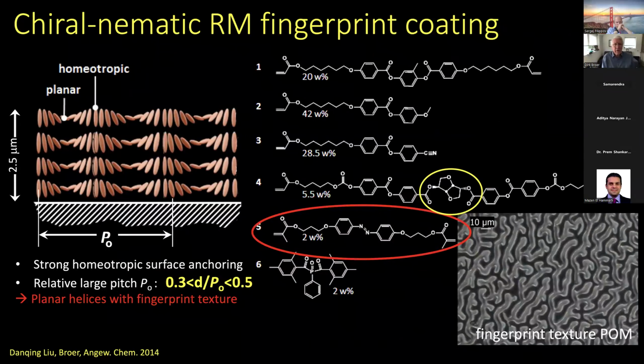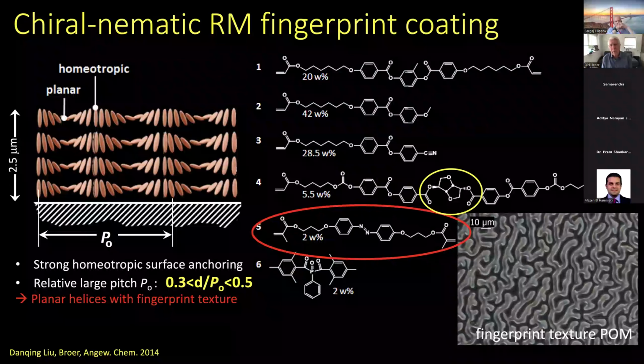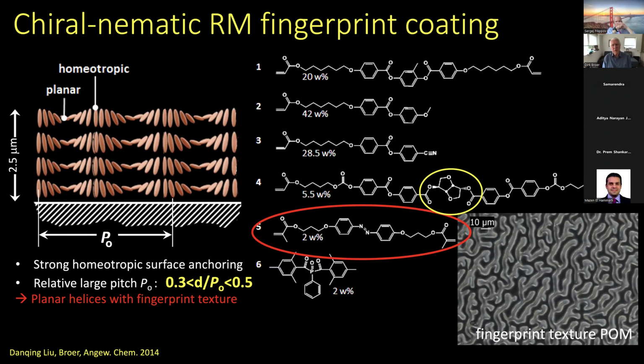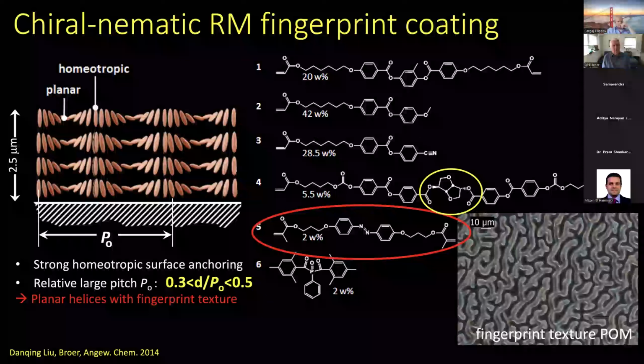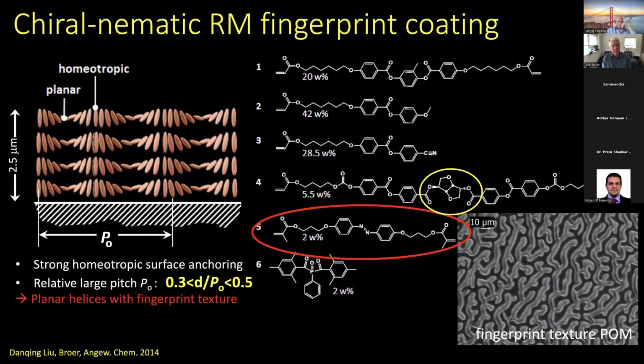So having developed this, we actually want to get rid of this mask-wise exposure of these films, and for that we decided to rotate the helix axis to go to a so-called fingerprint texture. Normally, if you put a chiral nematic material on a substrate, the axes are more or less perpendicular to the substrate, but by playing a little bit with the anchoring conditions at the substrate, and by optimizing the ratio of thickness over the pitch of the helix, you can create a condition where helices are formed parallel to the substrate.